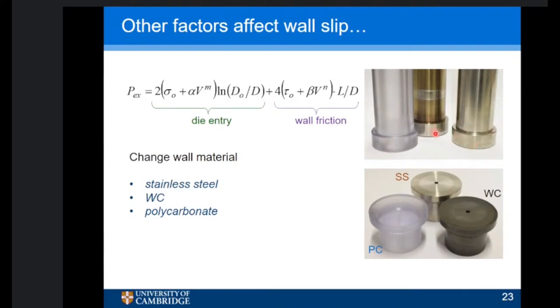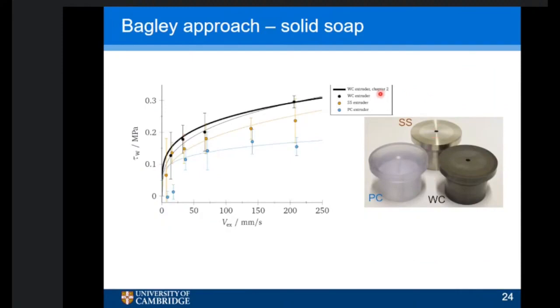So what we're going to do is show you the results for extrusion of a given material through these 3 things, identical tests, and what happens to the wall shear stress and slip behavior. And again, using this Bagley approach, this is for solid soap. Here's your wall shear stress. Here's your extrusion velocity, so the slip velocity for these materials. The blue one is for the polycarbonate. The orange ones are for the stainless steel, and the black ones are for the tungsten carbide kit. And the line is from an approximation used elsewhere.